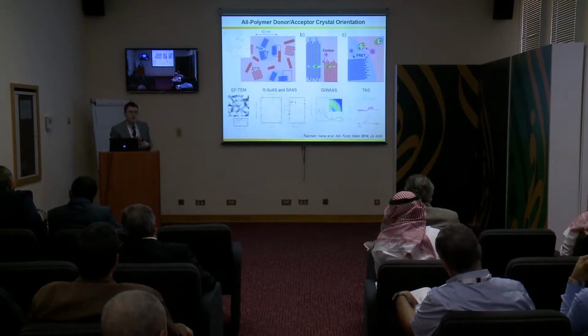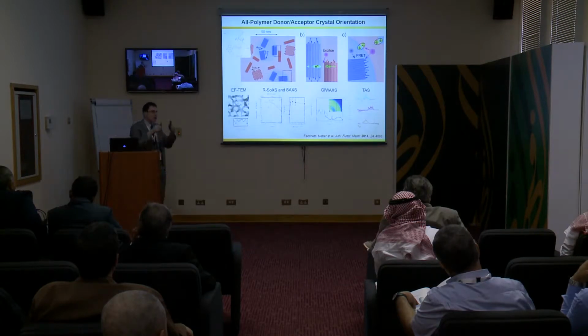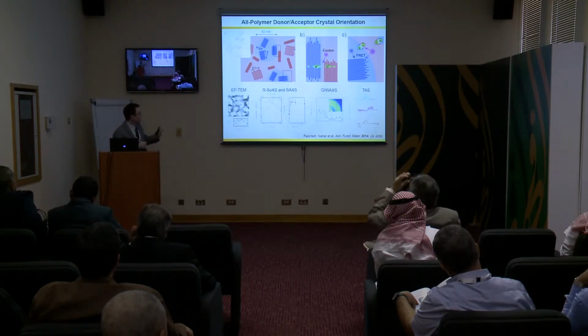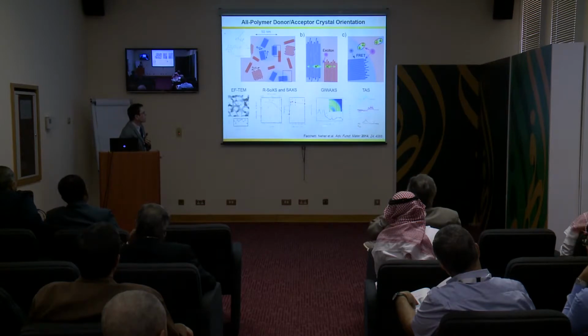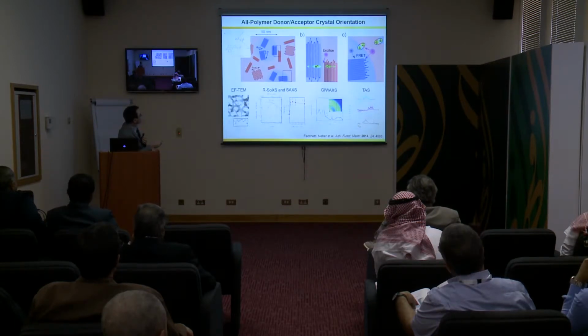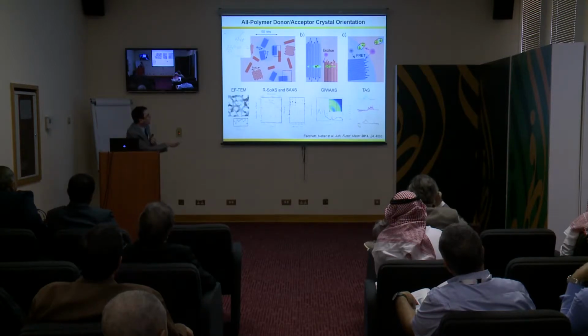And it's very important. This is something you need to worry about when you make polymer-polymer blends: how these two domains get together. This is the work done by, I would say, completed by the group of Dr. Neher, using some of our polymers, really having a continuity at the interface between the donor and acceptor polymeric domains is very important to really enable the splitting of the excitons.